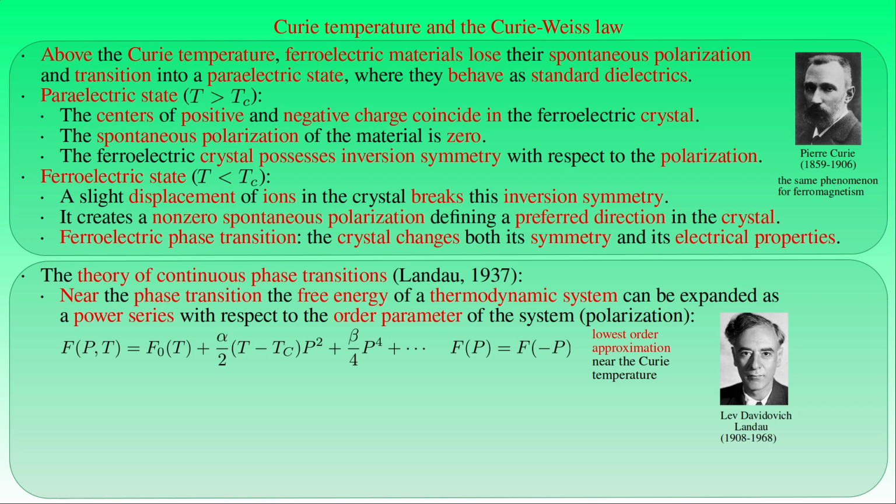In the standard expansion of free energy, all the coefficients are temperature-dependent and they have to be expanded with respect to the temperature. However, the leading term in such an expansion of the coefficient of the quadratic term must vanish at the stationary point, and the lowest order term in the expansion with respect to the temperature is proportional to the difference between the temperature T and the Curie temperature Tc. This is not the case for the coefficient of the quartic term, where the leading term of its expansion with respect to the temperature is a non-zero but dominant term for vanishing polarization. Then the dominant coefficients of the higher order terms can be approximated by constants.